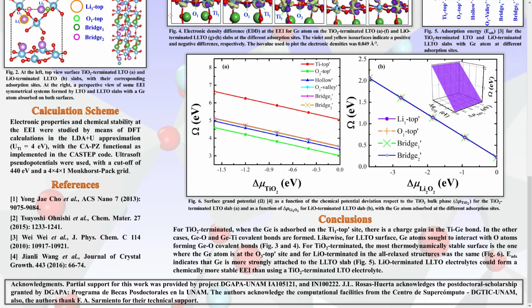For the titanium dioxide termination, the most thermodynamically stable surface is the one where the germanium atom is at the oxygen top site, and for the lithium oxide termination all relaxed structures are the same. Figure 5. Absorption energy indicates that germanium is more strongly attached to the lithium oxide termination. Figure 5. Lithium lanthanum titanium electrolytes with a lithium oxide termination will form a chemically more stable electrode-electrolyte interface than lithium lanthanum titanium electrolytes with a titanium dioxide termination.